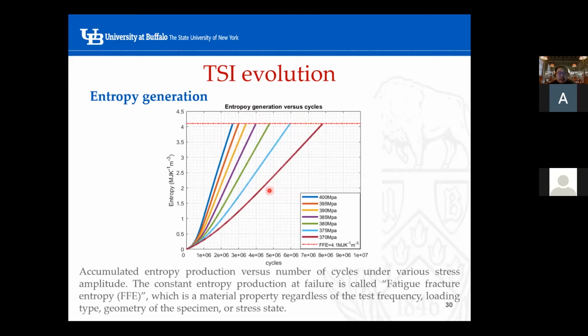Here I'm showing you the stress amplitude versus the entropy production from different stress amplitudes. We have around 1, 2, 3, 4, 5 — around 7 different sets of data. We ran them all and tested their frequency, and at failure they all created the same amount of accumulated entropy.